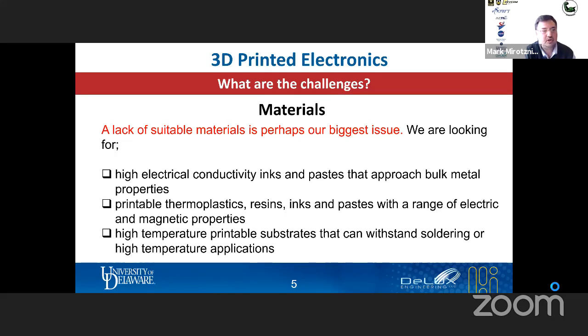Doing functional electromagnetic devices at, in our case, very high frequency, we want to get up to W-band, 110 gigahertz if we can, but certainly up to 30, 40 gigahertz. There's a big problem in getting the right materials. For example, the electrical conductivity of the inks or the paste that we can print is usually an order of magnitude below bulk properties and progressively gets worse at high frequencies.